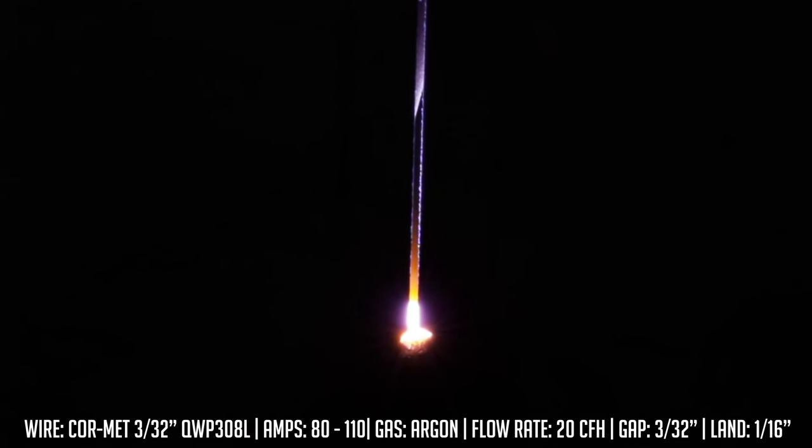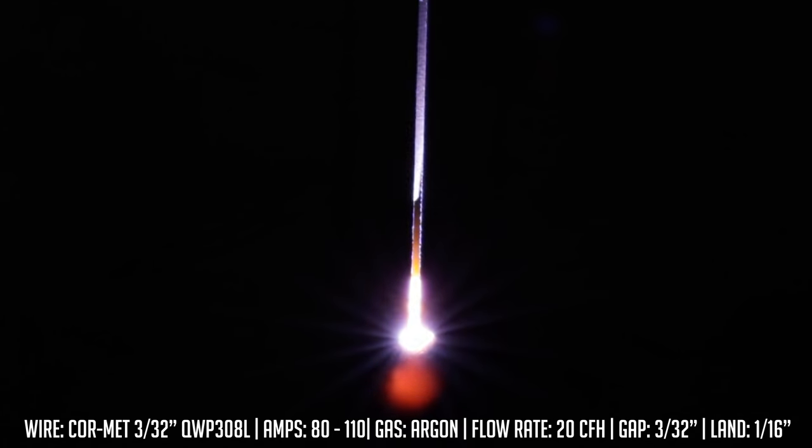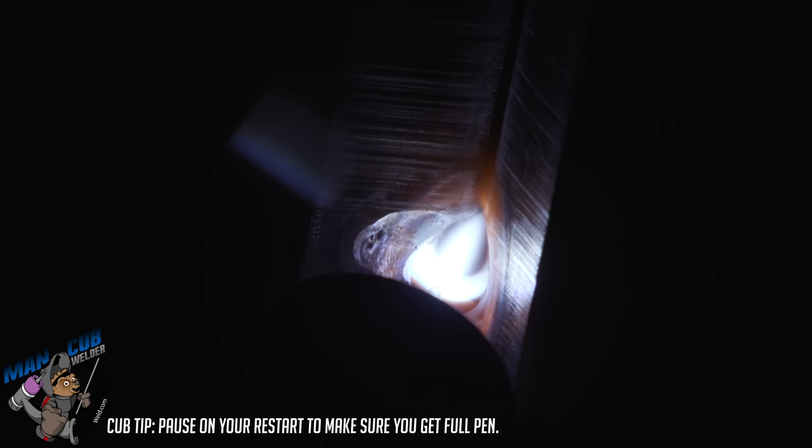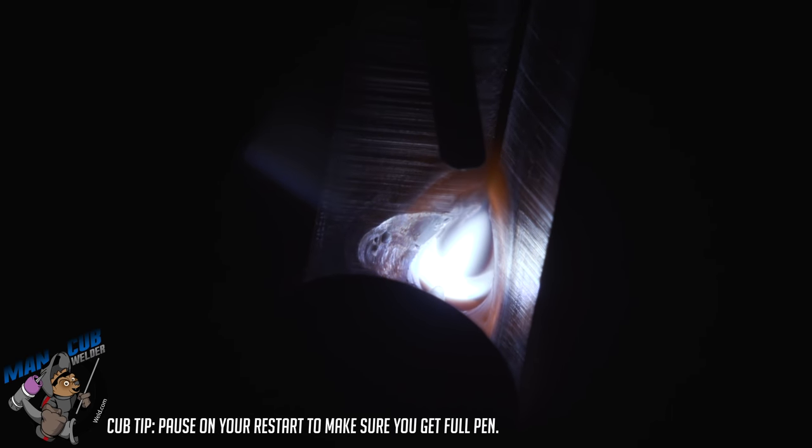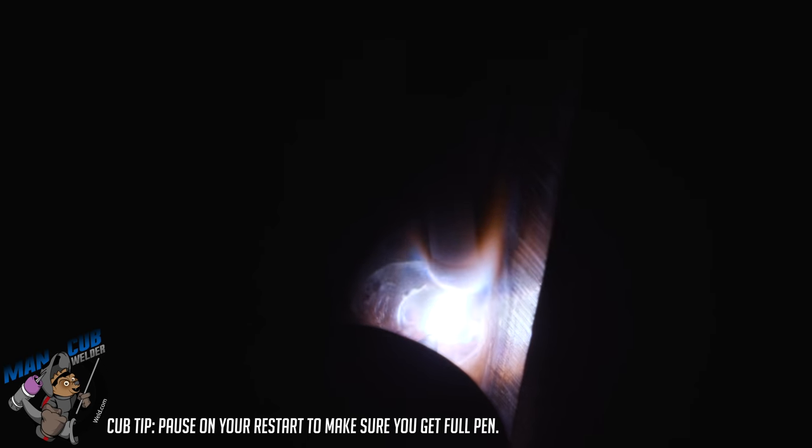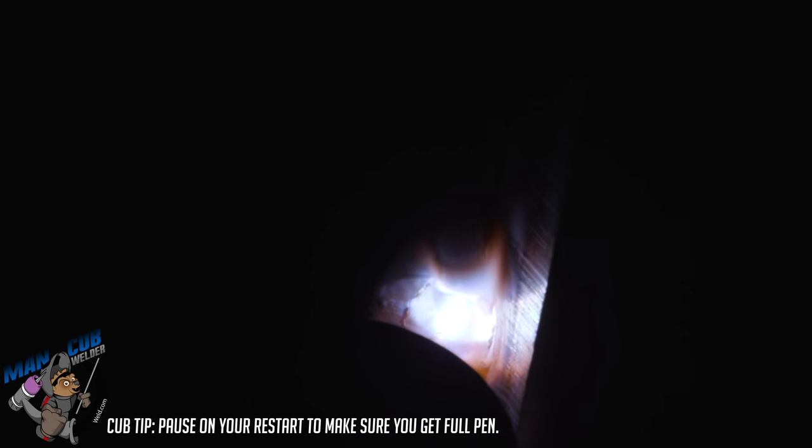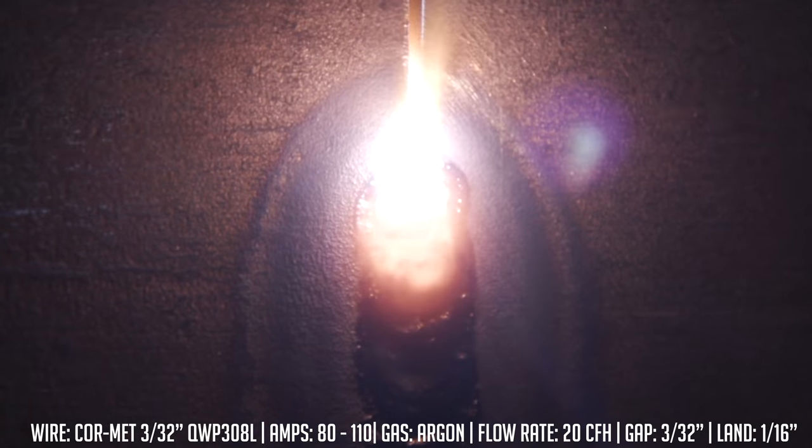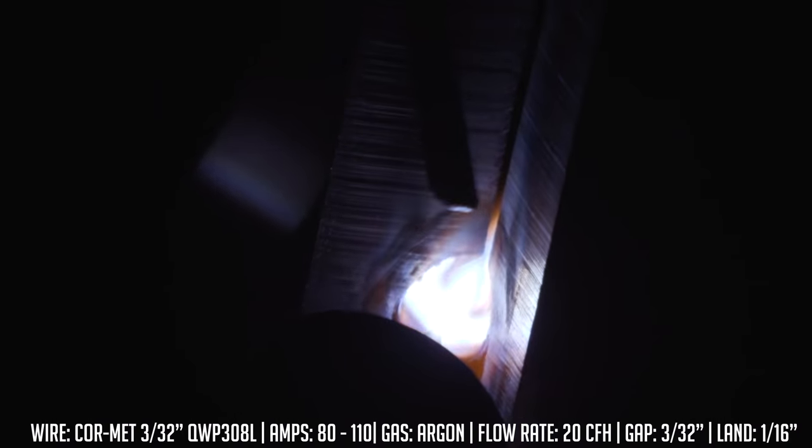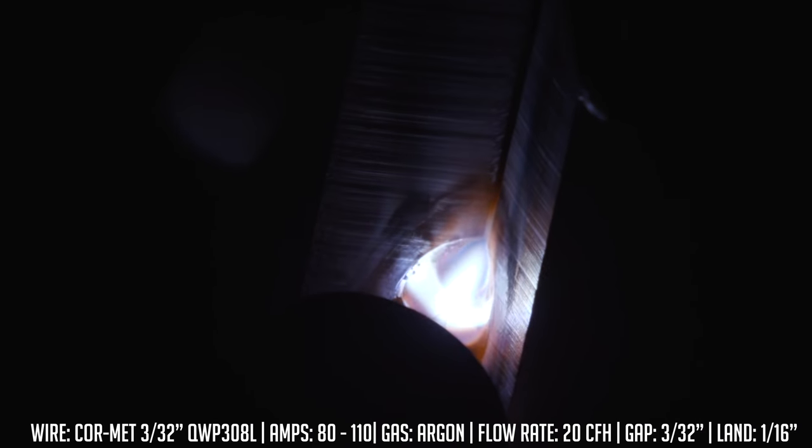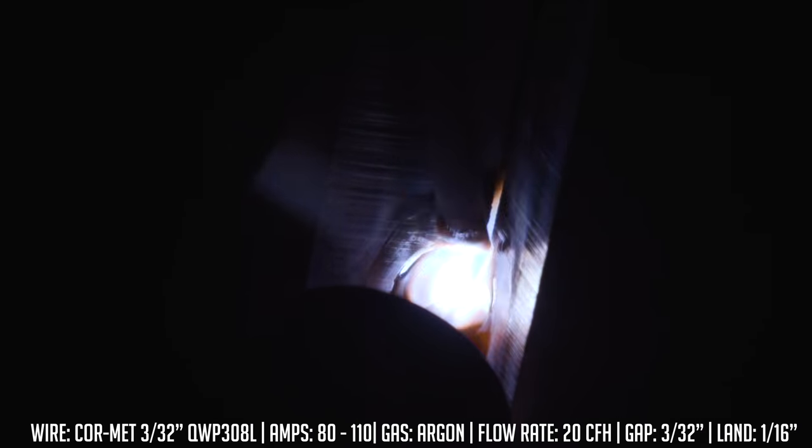I'm going to strike an arc, start about a quarter inch back from the top. Get a puddle forming here, walk on it very slowly. I'm at the edge of it, gonna sit there and pause, let that puddle melt through all the way, make sure I'm breaking down the metal plate there real good. Then we're going to resume our same action - push it, dab it in, push it up with the tungsten.